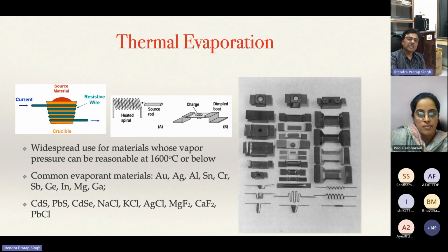That is one advantage. Another thing is that thermal evaporation or electron beam evaporation is normally done for materials which do not have a very high melting temperature. The reason is that you need some kind of support, so you put your material inside the boat to evaporate it. You are actually heating the boat and that heat is getting transferred to the material. So there is a chance that the source material can interact with the boat material. That is another disadvantage of thermal evaporation methods. So sputtering is preferred in that sense: you get a uniform film, and also you use the whole target.